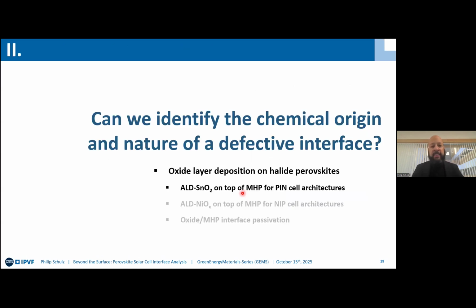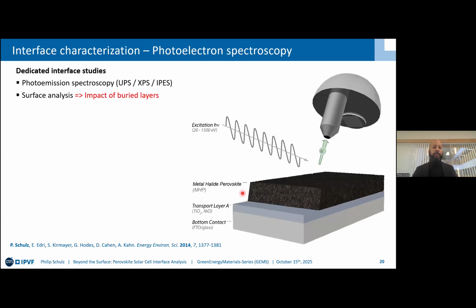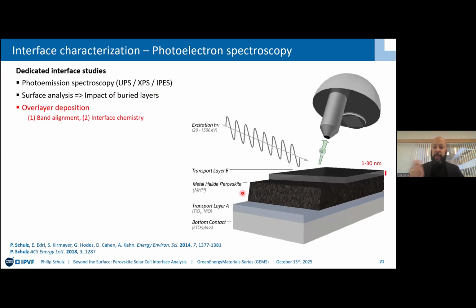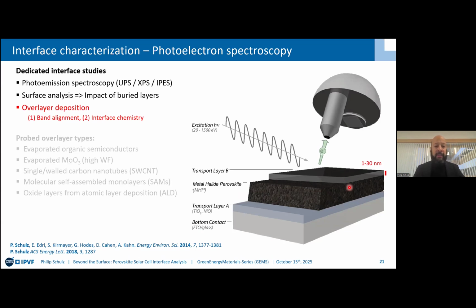So let's see how we can actually now also use HAXPES in order to identify the chemical origin and nature of defective interfaces when it comes to oxide perovskite interfaces, to understand what is the driving factor for the degradation, but also for these performance losses. So we tweak the experiment a little bit. We now not only look at the surface of the perovskite, but we actually put an overlay on top in order to look into band alignment and also this interfacial chemistry.